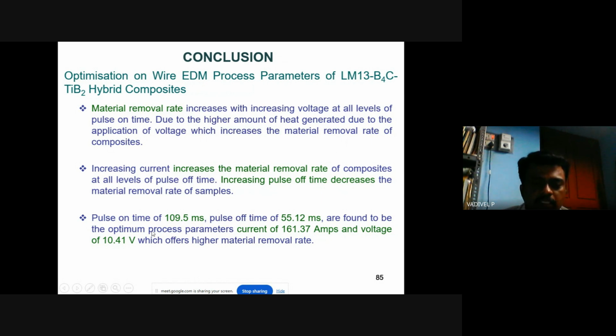The pulse on time we obtained is 109.5 milliseconds, and the pulse off time is 55.12 milliseconds, with a current of 161.37 amps and a voltage of 10.41 volts, which are found to be the optimum process parameters offering a higher material removal rate. So these are the optimized values we obtained here.